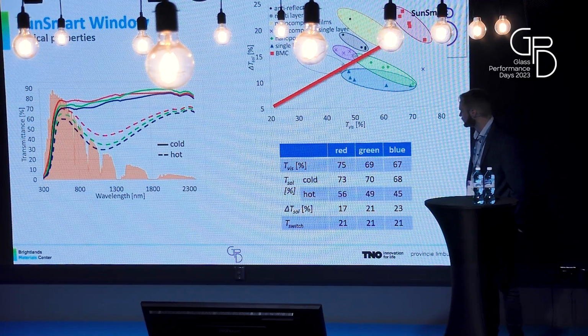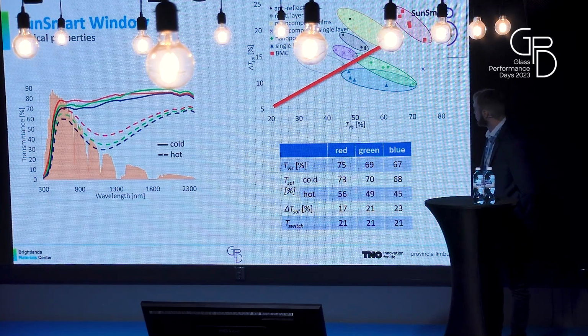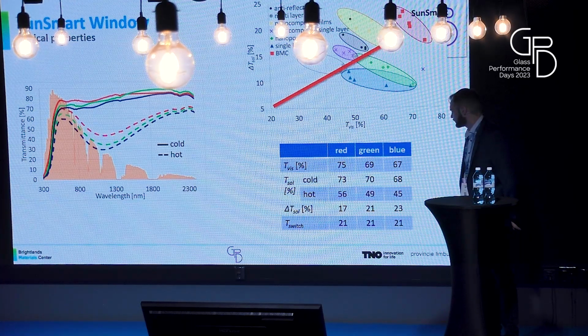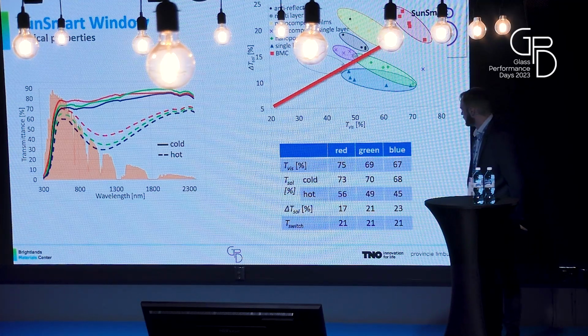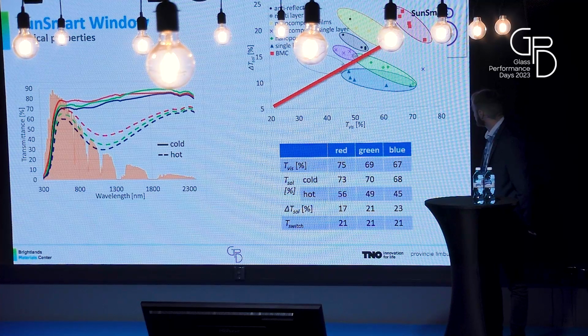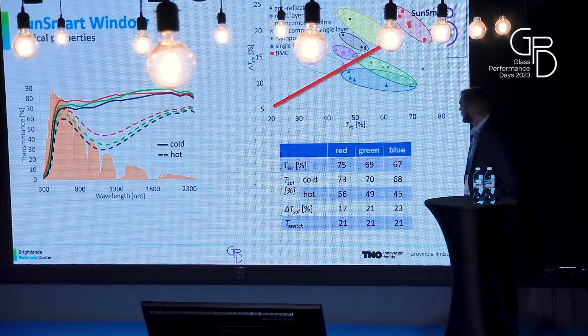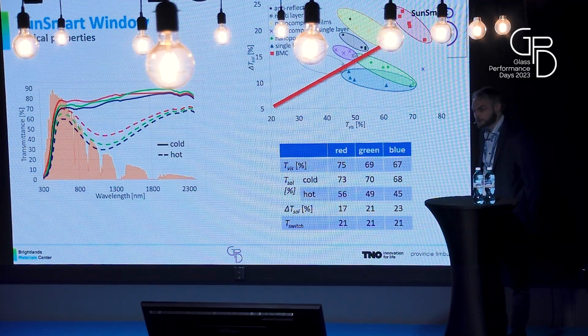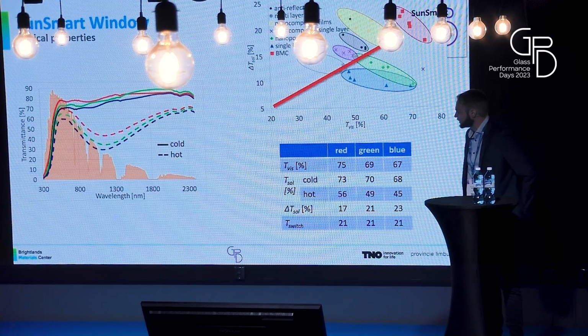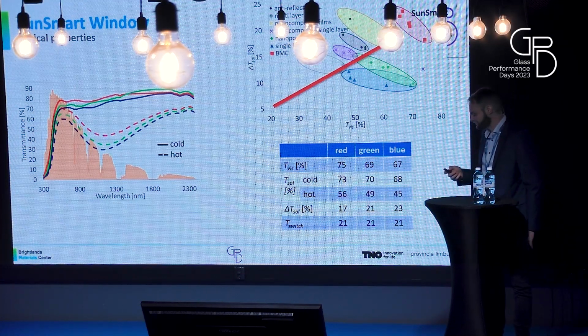And these are just some of the materials that we have produced, where we can reach visible transmissions of up to 75%, and solar modulations with one of the materials of up to 23%. And you see that it's really exceeding everything else which has been published in literature on these kinds of materials before. I said that the most important area is between 800 and 1400 nanometers.